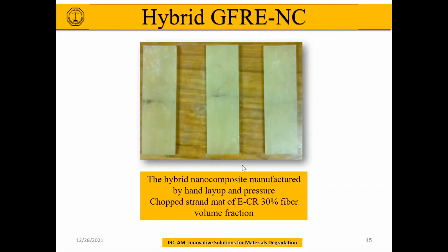This is another project that we have done. We have made a hybrid nanocomposite. That means the matrix here is not the epoxy by itself, but it is epoxy with nanoclay. And we used hand layup and pressure. We used chopped strand mat and fibers at a volume of 30%.